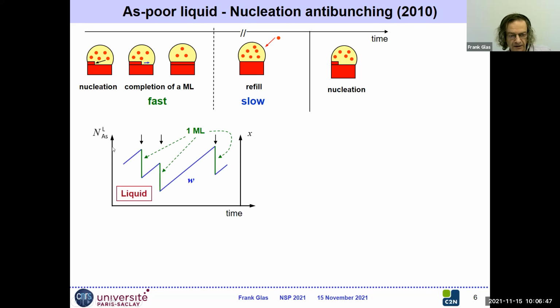Now, if we look here, schematically, at the variation of the number of arsenic atoms in the liquid, or the arsenic concentration, again, they are proportional. So it increases up to a point, the down pointing arrow here, where we have a nucleation. And then we expect it, very fast and in this limit instantaneously, to form a full gallium arsenide monolayer, which means that we deplete the liquid of the equivalent of 1 monolayer of arsenic. So we're down there. Then the external fluxes refill the droplet, so the concentration of arsenic starts re-increasing. And then at another value, because it's a random phenomenon, we nucleate another layer. Again, we consume a full monolayer of arsenic from the liquid to form a full monolayer, and then we have refilled. So that was the picture we had.